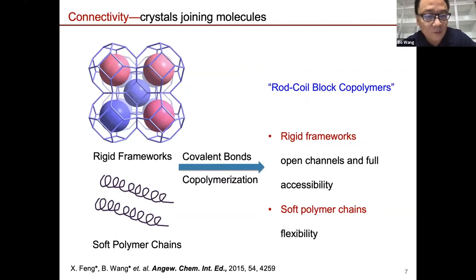If we want to make a film or a membrane out of it, we have to make it rather flexible. When we look at this problem, we think, can we link those rigid frameworks up with soft polymer chains through covalent bonds by a copolymerization process? We learn from simple polymer chemistry, which has rod-coil block copolymers. So can we use the MOF or COF particle as a monomer to copolymerize with other monomers, eventually giving such a structure, so that we have rigid domains that give open channels and full accessibility to the active sites, and soft polymer chains that give flexibility and processability.